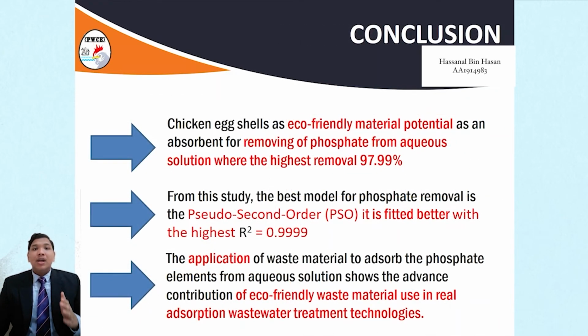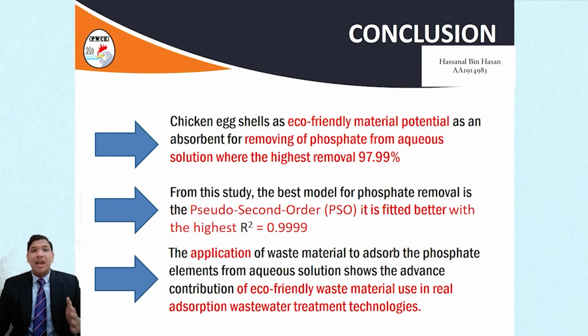From these studies, it can be concluded that chicken eggshell, as an eco-friendly material, has potential as an adsorbent for removing phosphate from aqueous solution, where the highest removal is 97.99%. Next, the best model for phosphate removal is the pseudo second order (PSO). It fits better with the highest R2 equal to 0.9999. The application of this material to adsorb phosphate from aqueous solution shows the advanced contribution of eco-friendly waste material used in real adsorption wastewater treatment technologies.